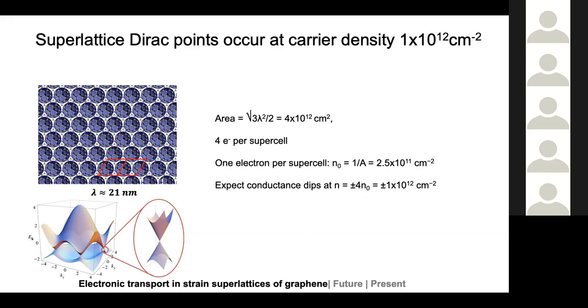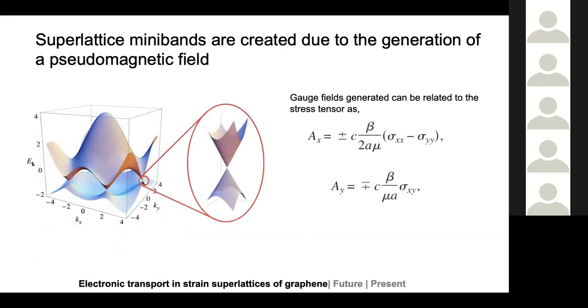To explain it further, we assume what actually happens is that the strain leads to creation of certain gauge fields which can generate a pseudomagnetic field. Why is it called a pseudomagnetic field? Because the effect of this field is very similar to what you would have if you have an external magnetic field. Because of this pseudomagnetic field, there are additional bands created near the Dirac point. You can see that this curve over here, they meet fairly simply at the Dirac point. There will be more features which show up in this region, and that leads to the formation of the secondary Dirac points, which lead to those dips in conductance.